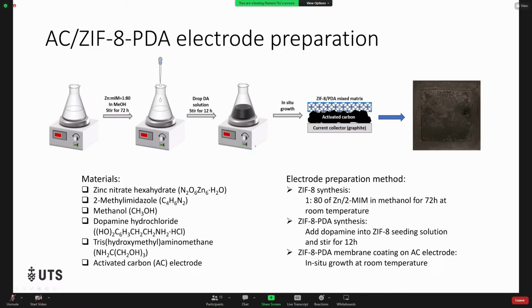So here is the electrode preparation process. I used zinc and 2-methylimidazole in methanol for 72 hours at room temperature. And then by adding dopamine into the ZIF8 seeding solution and storing for 12 hours, the ZIF8 polydopamine can be synthesized. After that, I use an in situ growth method to coat the ZIF8 polydopamine membrane on the activated carbon electrode. And here is an example of the modified electrode.